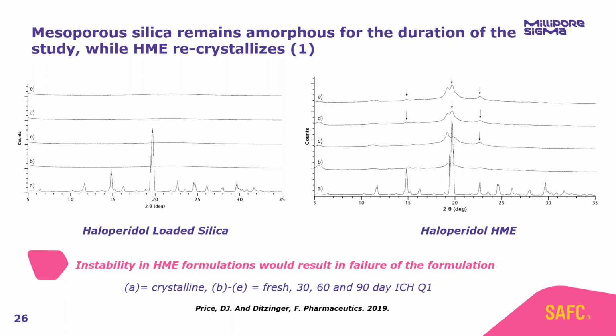And furthermore, we've continued these measurements naturally, and we can now see 12-month and soon 18-month stability. These molecules are stable in the amorphous form with our mesoporous silica. The situation was slightly different for haloperidol HME. Again, crystalline haloperidol is at the bottom, then we have the fresh sample. And what you can see from the fresh sample is we are already seeing some evidence of microcrystallinity here. So it's not a perfectly amorphous structure. And these peaks simply grow as the time progresses. So the haloperidol is not stable in the amorphous form in this hot melt extrusion formulation.